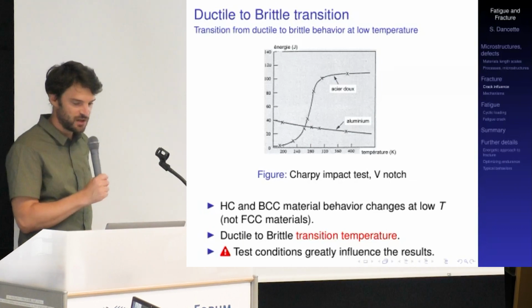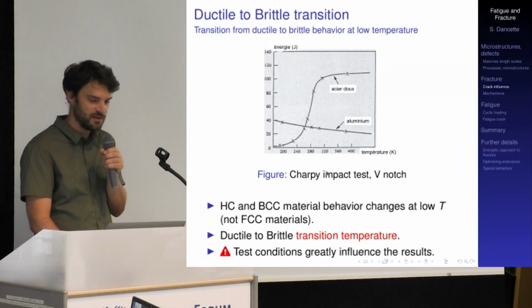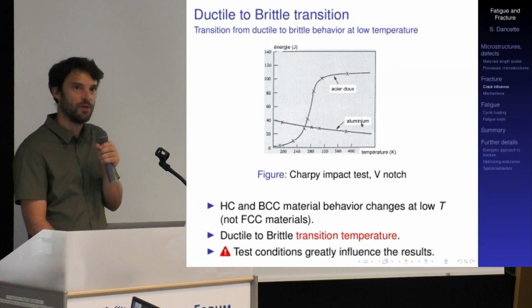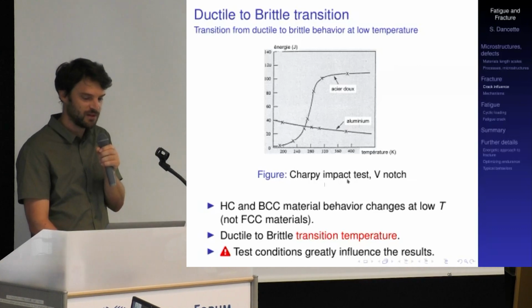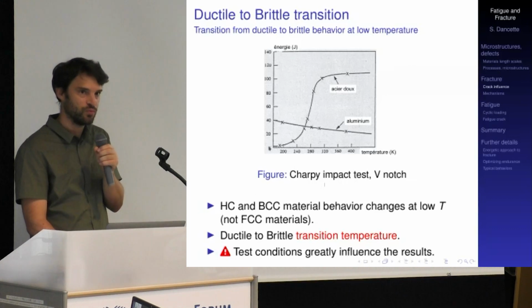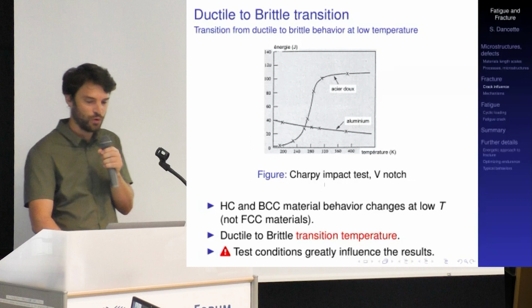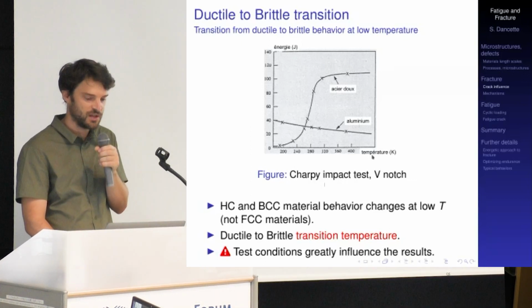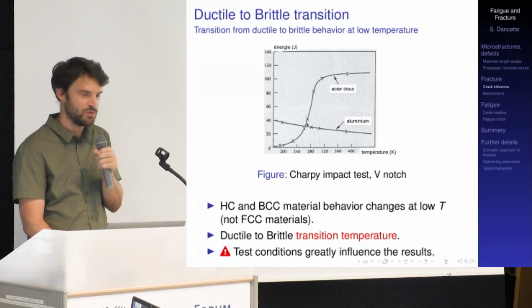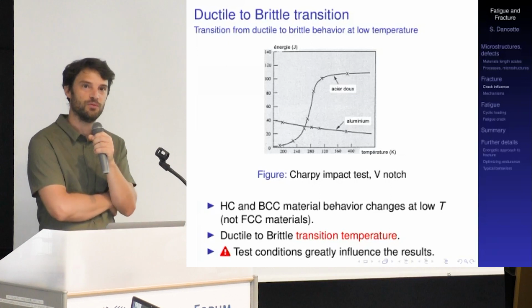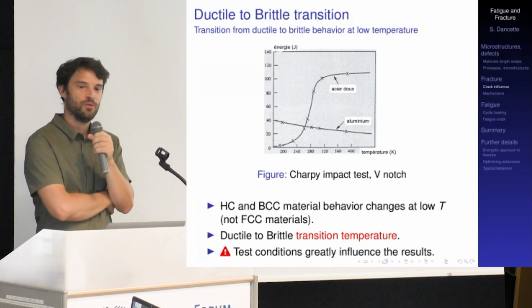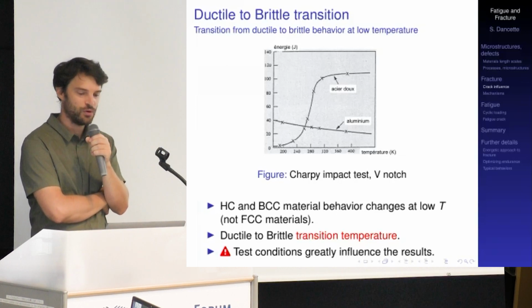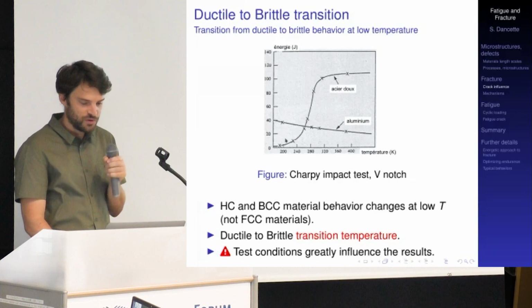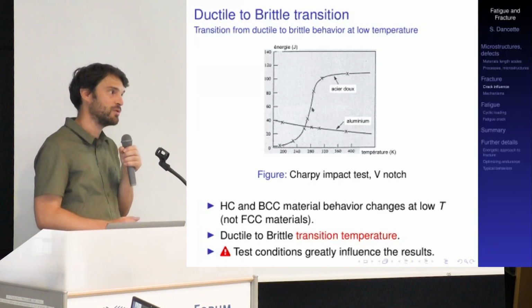But still, if you perform that kind of impact test, Charpy impact test for example, you can easily see in that picture here, which is in French, I'm sorry, that this is mild steel, this is aluminum. You can clearly see how steel will tend to present a decreasing fracture energy when you lower the service temperature, so the temperature of the mechanical test. And most of the steels, especially maybe 100 or 150 years ago, were not really precisely controlled in terms of chemical composition and so on. And 100 years ago, it was not uncommon to have that kind of ductile to brittle transition at temperatures close to room temperature, in fact.